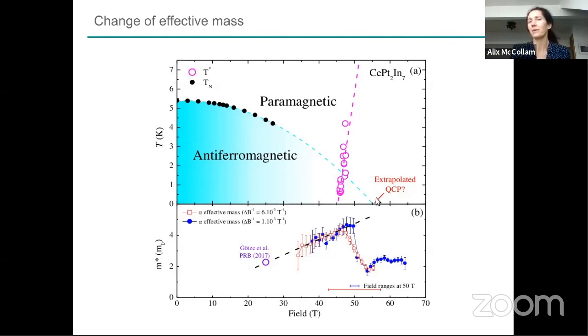So the extrapolation was done really thinking about the phase diagrams of CeRhIn5 and CeIn3 and the other members of the family. So there's not much physical basis for this extrapolation. It could indeed come down here, or it could come down much more sharply. As I said, it's somehow slightly mysteriously difficult to measure this antiferromagnetic transition. We don't see it in magnetization. We can't see it in the ultrasound. It doesn't show up very clearly. It doesn't have a clear signature.